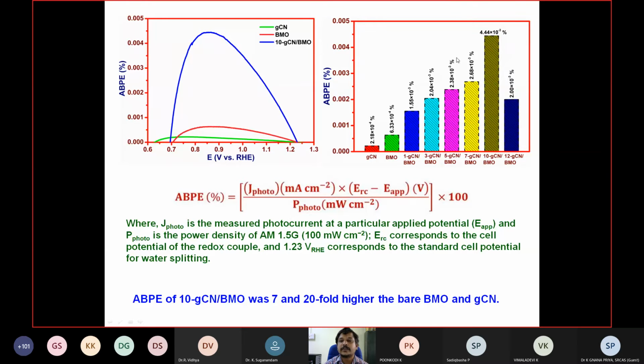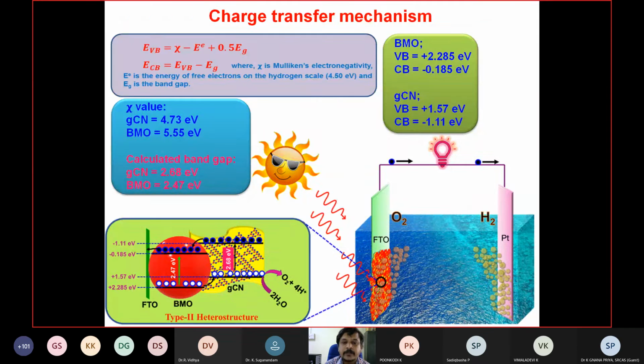Especially look at this: the 10 weight percent of graphitic carbon nitride in bismuth molybdate shows 7-fold and 20-fold higher efficiency than the pristine materials, because those materials undergo high charge recombination. That charge recombination is suppressed by forming the heterojunction between these two materials. You just make a note of this value, 4.44 into 10 to the power minus 3. In what way we will further improve this efficiency, I will explain later.